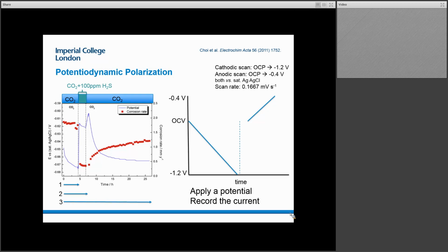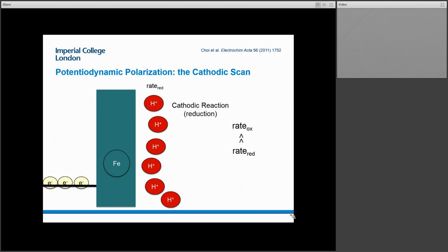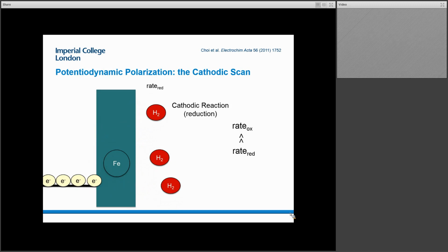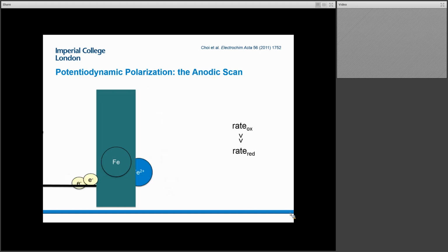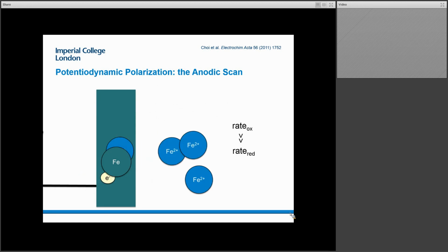And so they ran 3 independent experiments. I think that's important to point out, running only to the completion of the stage, since this particular type of scan can, of course, create a history in the sample, therefore making it unable to follow the time series. But what's lovely is, in that cathodic scan, we have the introduction of electrons, which allow the reductions to take place. And so the rate of reduction in this region is going to be significantly more significant than the rate of oxidation. By contrast, when we move to the anodic scan, we have the reverse situation where our rate of oxidation is going to be significantly larger than our rate of reduction.